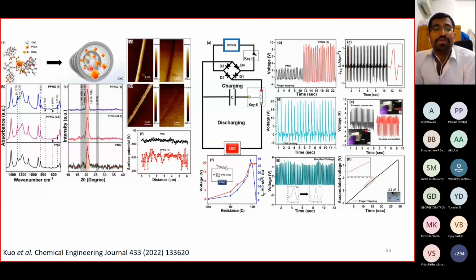And this kind of perovskite structure, we already know it's going to create some piezoelectric outputs that will have some crystal deformation. If you are going to apply the stress on it, then eventually you'll be getting this kind of dipole alignments and changes with respect to your stress condition. So with the help of that, we can see the difference among conventional structures. And when we are going to blend some perovskites, what happens? The voltage is getting tripled. So it's quite good for the application part.